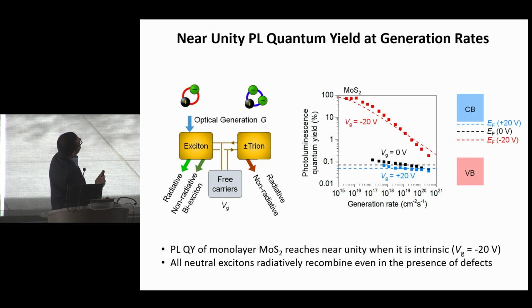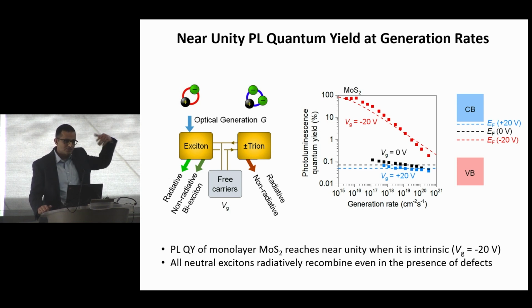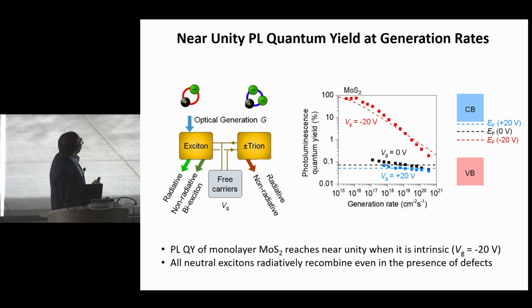Now, in a free carrier system, if you have any defects, the free carriers will non-radiatively recombine with the defects. In an excitonic system, the only way the excitons can interact with the defect is for them to split. And once they split, then they can undergo Shockley-Read-Hall, the SRH. But in the case of monolayers, the binding energy of the exciton is on the order of 1 electron volt. It's very difficult to split these excitons.